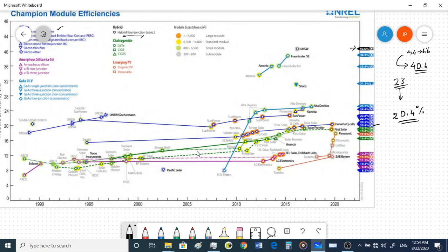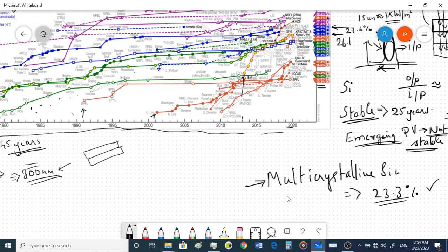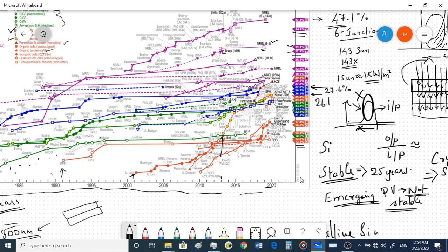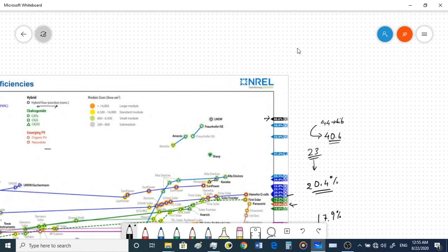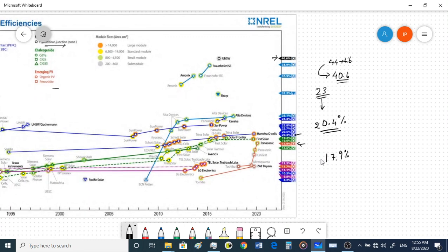Now if you look at some of the emerging technologies, it is reported that the perovskite solar cells have an efficiency of 17.9% on a module. But if we look at the highest efficiency that has been reported, you can see that it is 25.2% for the perovskite solar cells. So that is the difference that you can see when we go from the lab scale cell to the module. It has come down from around 25.2% to 17.9%, since when you manufacture it on a module scale, the efficiency that you get for a single cell cannot be matched by that of the module. So that is a major problem in commercializing these cells.